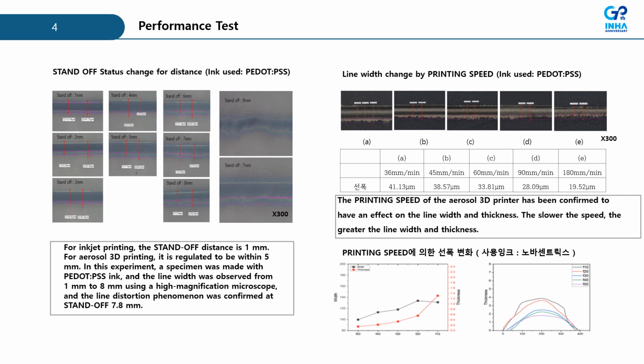In this experiment, a specimen was made with PEDOT:PSS ink, and the line width was observed from 1 mm to 8 mm using a high magnification microscope, and the line distortion phenomenon was confirmed at the standoff of 7-8 mm. The figure on the right measures the change of line width by the printing speed. It was confirmed that the printing speed of the aerosol 3D printer has an effect on the line width and thickness.